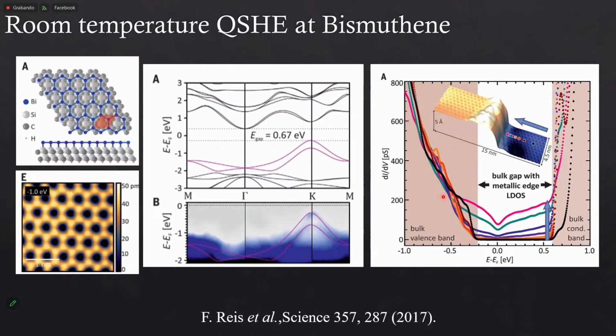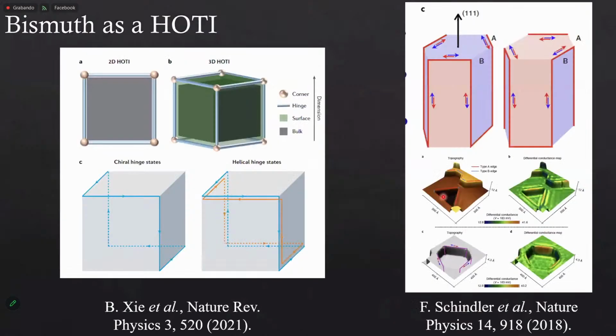And something that's interesting is that bismuth, because of this very high spin-orbit coupling, does not show only this phase. There are also other kinds of topological phases that can appear when you add more ingredients to it. One ingredient that you can add is crystalline symmetries. There was some work showing that if you add these crystalline symmetries, you can have states that do not only live on the surface of the material. Not something like the edge, but something called a higher-order topological insulator, where the states live in the corners of the system.